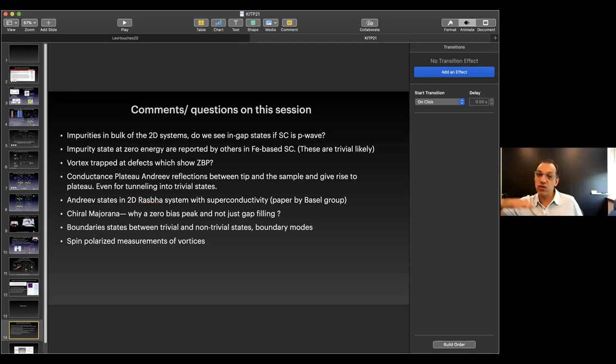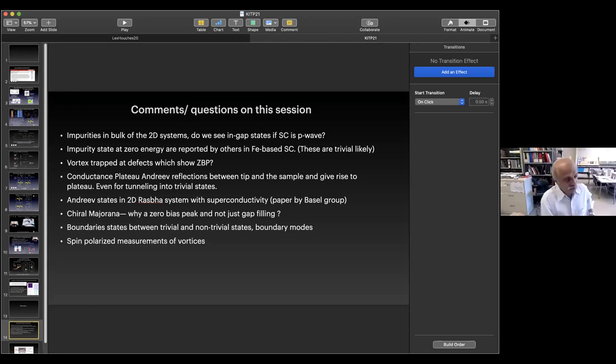So presumably, if you change the thickness of your europium sulfide, you can change the amount of band tuning that you get from the charge transfer. Yes. For example, as you saw, 0.9 monolayer shifts it by about 200 milli-electron volt, whereas 2 monolayers shifts it by almost 400, 450 milli-electron volt. After that, it doesn't make much difference.